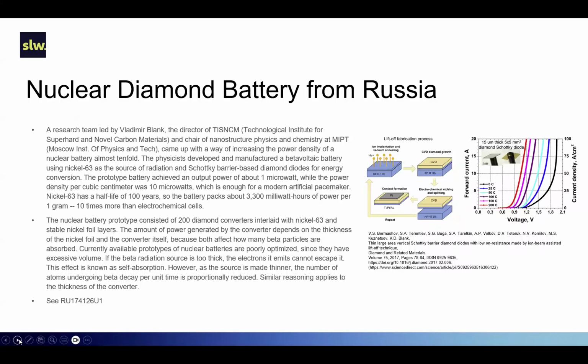A research team led by Vladimir Blank, the director of the Technological Institute for Super Hard and Novel Carbon Materials and chair of nanostructure physics and chemistry at the Moscow Institute of Physics and Technology, came up with a way of increasing the power density of a nuclear battery almost tenfold. The physicists developed and manufactured a betavoltaic battery using nickel-63 as the source of radiation and a Schottky barrier-based diamond diode for energy conversion. The prototype battery achieved an output power of about 1 microwatt, while the power density per cubic centimeter was 10 microwatts, which is enough for a modern artificial pacemaker.